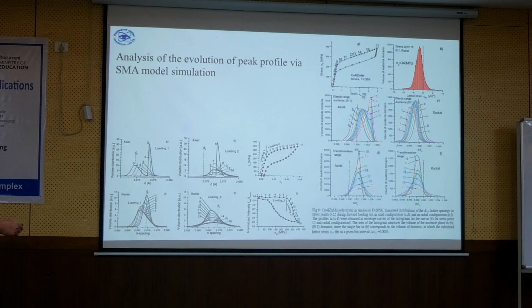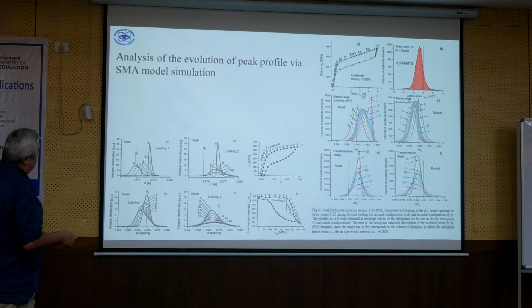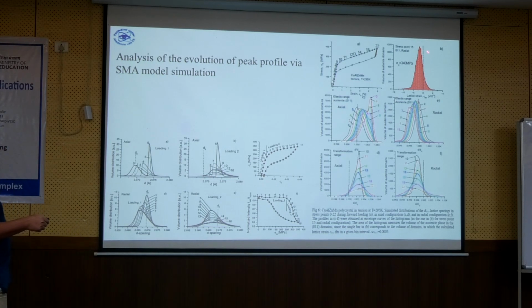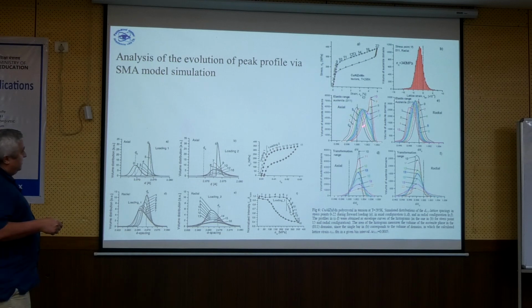One interesting point which I like on this was that we were able also to explain the shape of the peak profile. If you look on this here, this is like the austenite peak, and when we load it and measure in every one of these steps, we measure the profile of this step. And then we look at how it looks like. Maybe I can use only this. This is from the model. This is from the experiment.